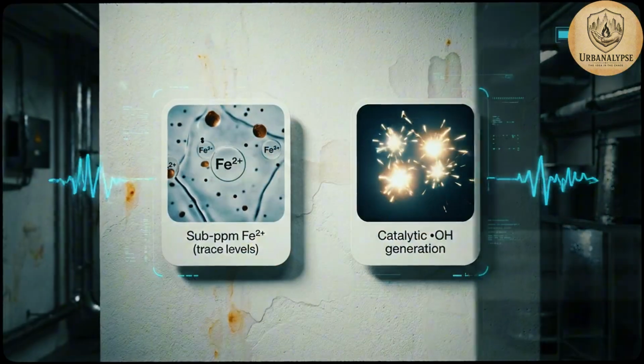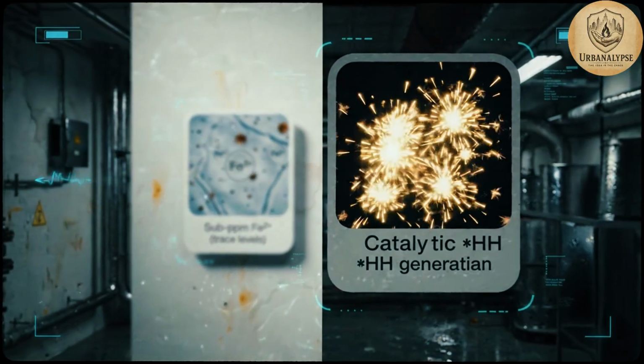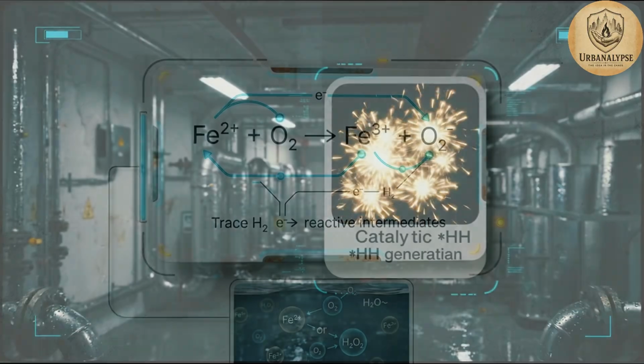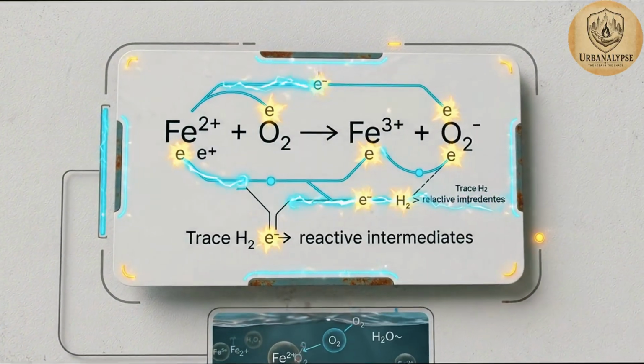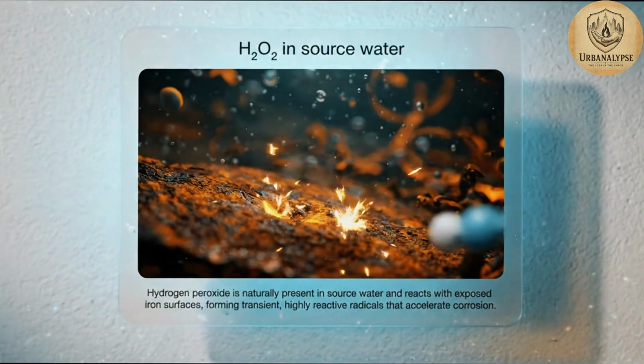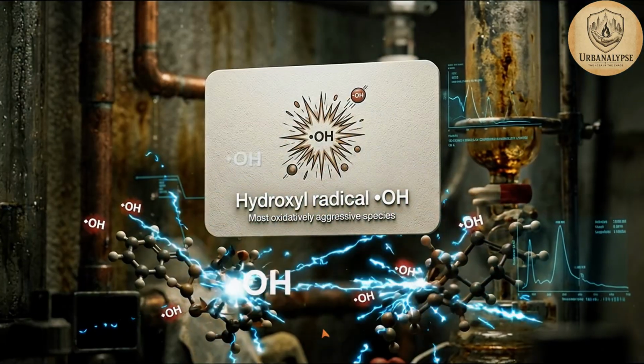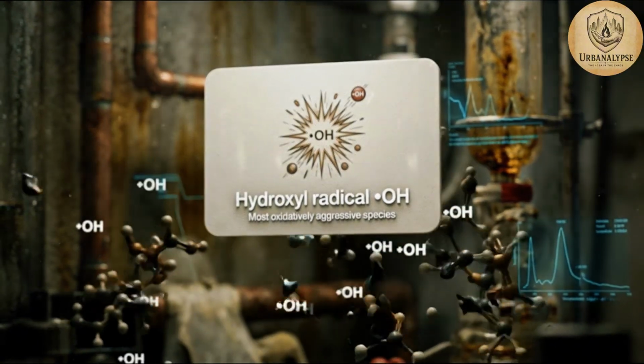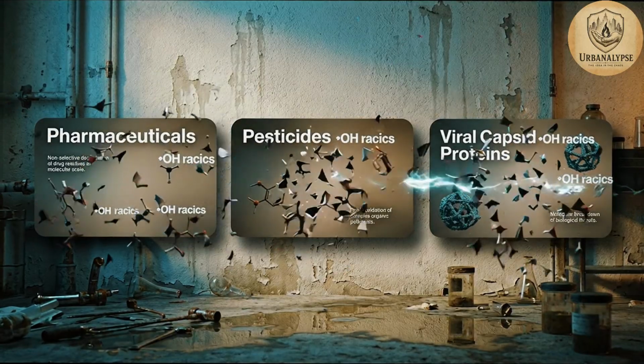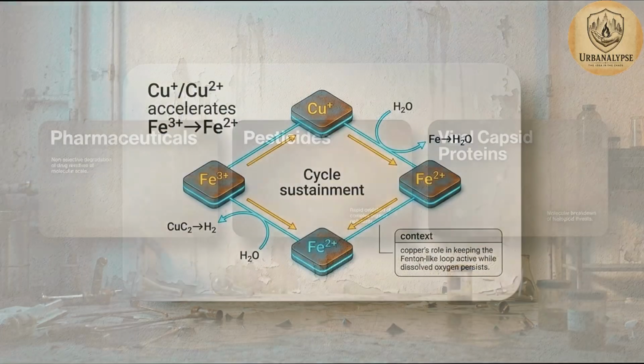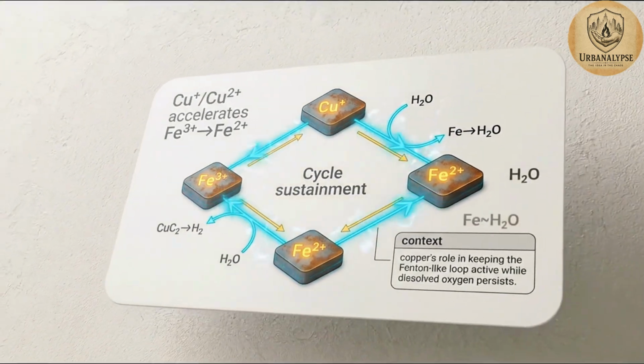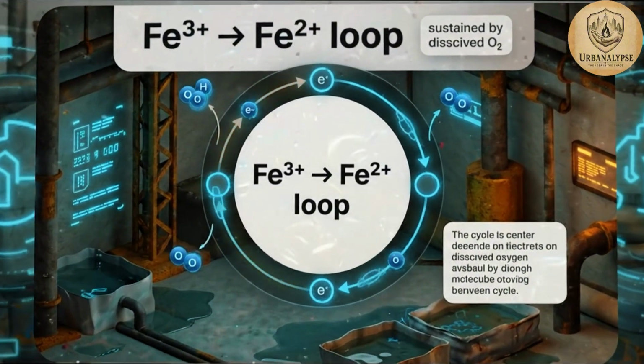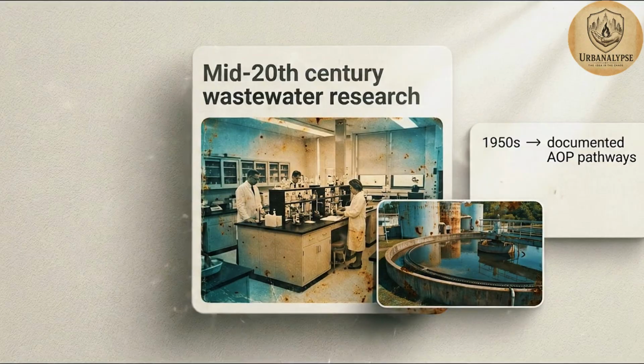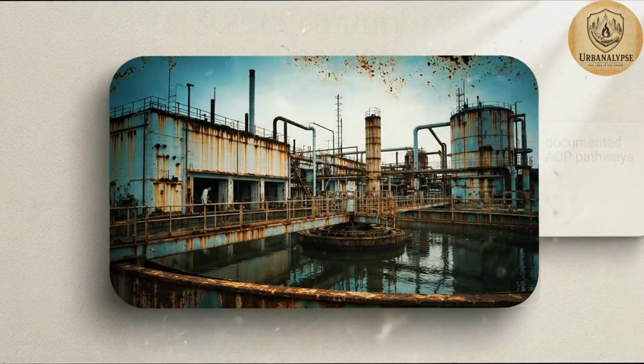Fenton-like iron catalysts. Counterintuitive fact: at sub-ppm concentrations, iron doesn't passively contaminate water, it catalyzes. Fe2+ reacts with dissolved oxygen or trace hydrogen peroxide, naturally present in source water, to generate hydroxyl radicals, OH. These are among the most oxidatively aggressive species in aqueous chemistry. They attack organic molecules without selectivity: pharmaceuticals, pesticides, biotoxins, viral capsid proteins. The catalytic cycle sustains itself because copper in the same system accelerates the back reduction of Fe3+ to Fe2+, keeping the loop running as long as dissolved oxygen is available.